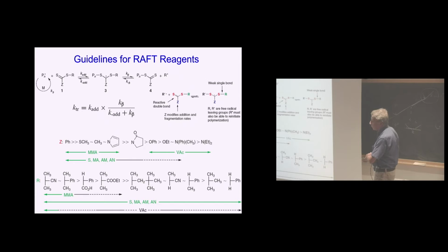For MMA, if you would use this, they would not work because they would propagate 100 times before exchange. If you would use, on the other hand, for vinyl acetate this one, it would form a persistent radical, it would not propagate at all. Also, it would depend on this leaving group. So this is designing of the initiator, very important for making block copolymers. So what kind of order of monomers should be there? Generally, if you have larger substituents, it's better. If you have groups which would stabilize the radical, like cyano or phenyl, it would also be better. So this would be good for methyl methacrylate, this would be good for vinyl acetate. So you need to have a certain selectivity there.